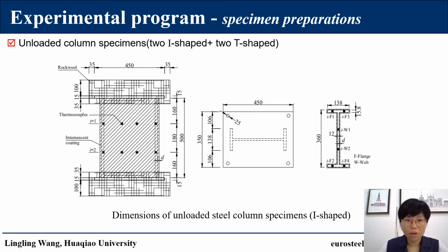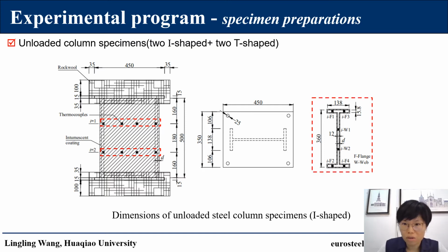The 4 unloaded column specimens consist of 2 duplicate I-shaped specimens and 2 duplicate T-shaped specimens. These specimens had primer and intumescent coating on all sides except the top and the bottom, which were protected by a 100 mm thick rock wool. Temperatures were measured at 2 locations along the column height and with 6 thermocouples at each location.